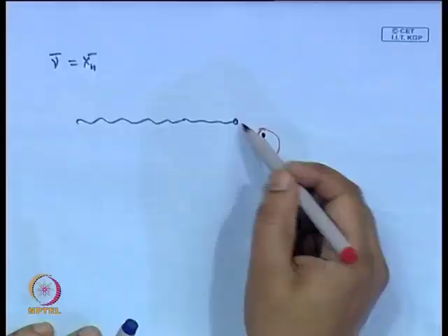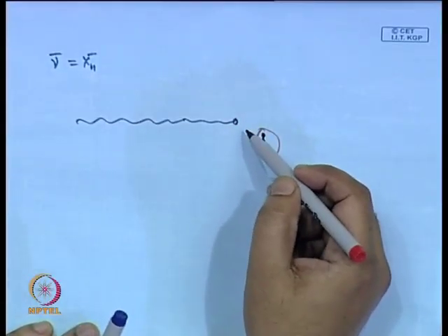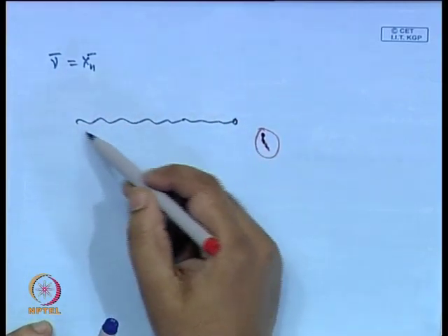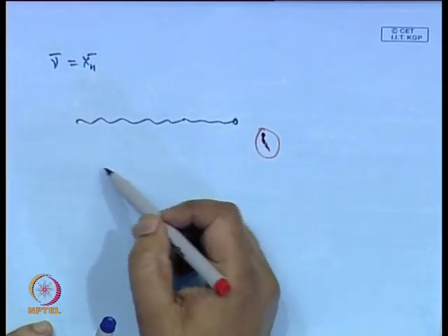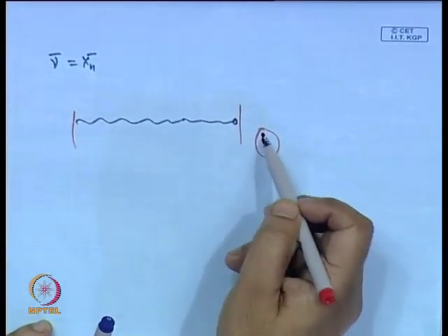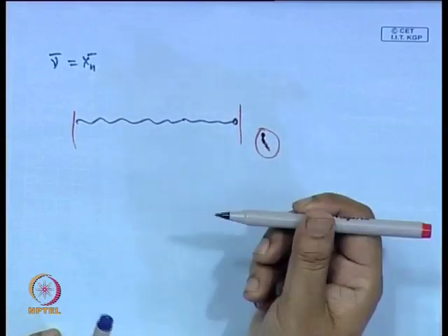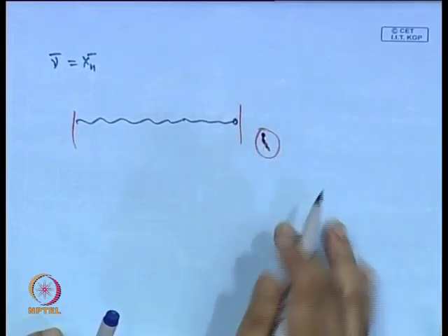So, whether they terminate by disproportionation or by combination, the size of the final dead chain is the same as the kinetic chain length. The size contribution due to this entering propagating radical is insignificant.